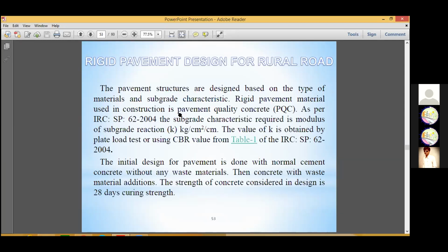For the rural road, the PQC, pavement quality concrete, is very important as per IRC SP 62/2004. The subgrade characteristic required is the modulus of subgrade reaction, K. The unit is kg per centimeter square per centimeter. The value of K is obtained by the plate load test or using CBR values from Table 1 as per IRC SP 62/2004. And initiate the curing and the compressive strength.